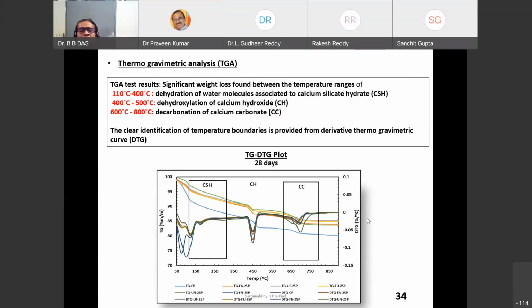Now, if you see a thermogravimetric analysis plot, this is my TGA plot, and you can see the peaks is my DTG, that is differential thermogravimetry. The TG percentage is presented on the left side, and the DTG percentage per degree is presented on the right axis. What will the left axis show? It will show the percentage mass loss. Suppose you take a sample at 100 percent, what percentage is lost at 900 degrees centigrade? That is basically your stability.